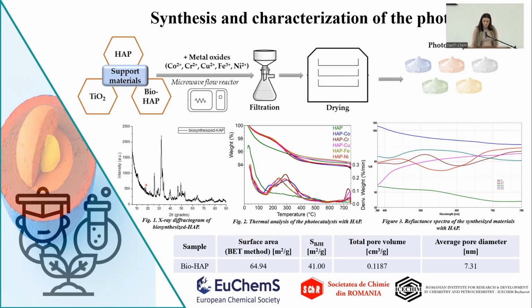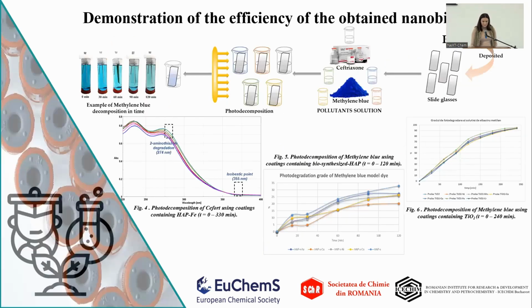The thermal analysis of the photocatalyst with hydroxyapatite revealed a residue of approximately 94% at 700 Celsius degrees. And we can see from the thermogram that the mass losses recorded are divided in 3 steps. Also, the reflectance spectra helped us to identify which compounds we obtained based on their color, and also to identify the wavelengths of the maximum absorption. The BET analysis, based on the average pore diameter of almost 7 nanometers, allows us to classify the materials obtained as mesoporous according to the International Union of Pure and Applied Chemistry.